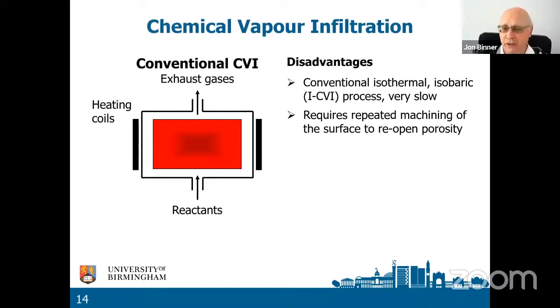There are some disadvantages. The conventional process, isothermal, i.e. same temperature, isobaric, i.e. same pressure, is very slow. What do we mean by very slow? We mean that making each component can take about 1,000 hours. And that's about 3 months of processing time. That is slow. Now, you don't make your components one at a time. You have a very big chamber, and you there can make a large number of components at the same time. But it is still slow.